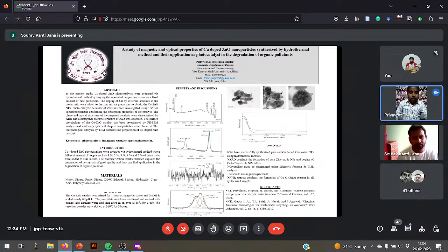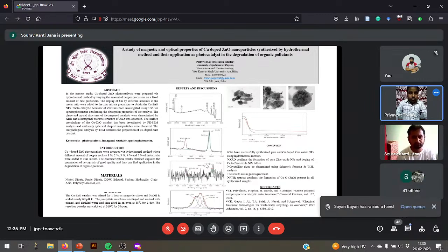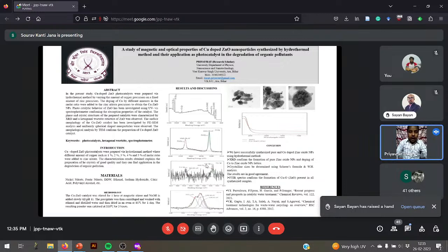The characterization techniques included XRD spectroscopy. The crystal structure and phases of each sample were determined using XRD, and field emission scanning electron microscopy (FESEM) and transmission electron microscopy instruments were used for morphology characterization. The photocatalytic experiments were carried out with reference to relevant scientific work, where 125 ml of solution and 25 mg of catalyst were added. The solution was then sonicated for 30 minutes in the dark to achieve adsorption and desorption equilibrium between the catalyst surface and the organic dye. Subsequently, the solution was exposed to visible light illumination. Throughout the experiment, the mixture was stirred with a magnetic stirrer, and at 20-minute intervals a liquid sample was taken and the catalyst was separated from the solution by centrifugation. The degradation of the dye was analyzed by measuring the change in absorption intensity.